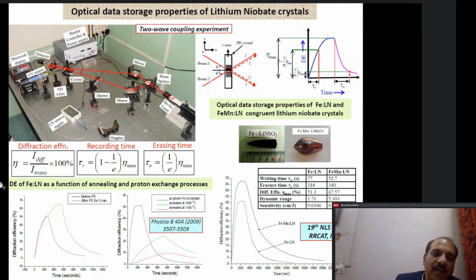So you will see there are three parameters which we measure from these experiments. One is called diffraction efficiency, another is called recording time, and the third one is called erasure time. These three are the main parameters which we have to characterize for any material which we think can be a good optical data storage material. In case of lithium niobate, we have done these experiments using two-wave coupling, for iron doped lithium niobate and also iron and manganese doped lithium niobate. And we have been able to show that iron and manganese double doped lithium niobate is a better material as compared to single doped material.